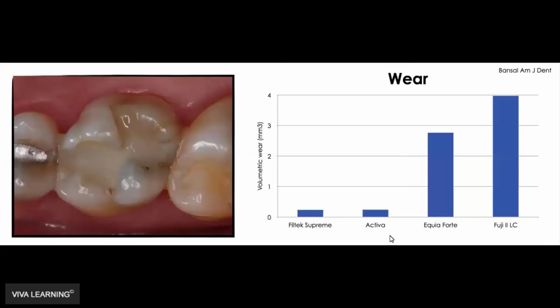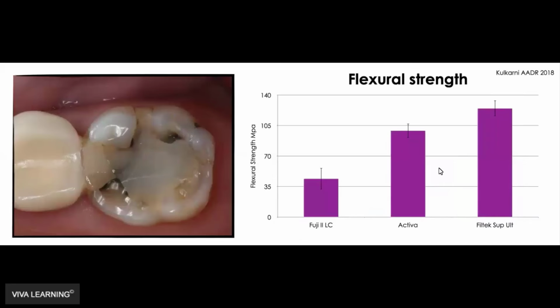Pretty much like a composite. Yeah, because you can see here as far as strength, maybe it's not the highest flexural strength, which, I mean, Filtek Supreme is usually one of the highest flexural strength composites we test. But Activa is right up there with the composite, at over 100 megapascals of strength. Whereas resin modified glass ionomer is not something I would use in the posterior to replace marginal ridges.